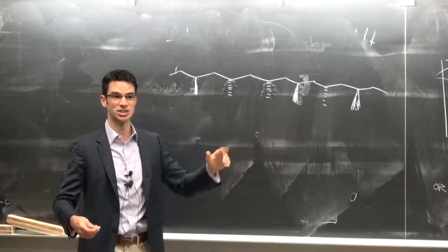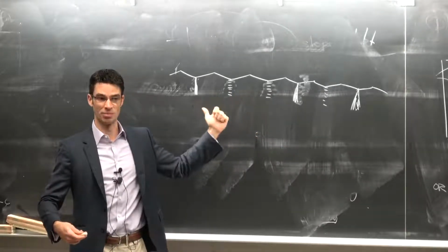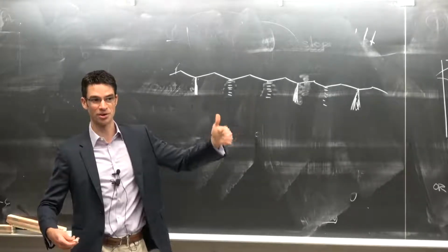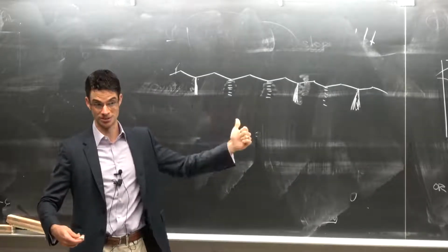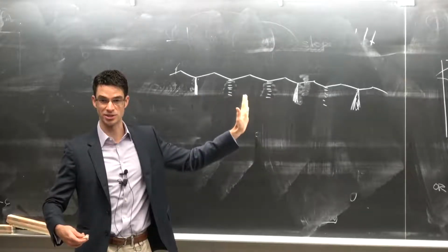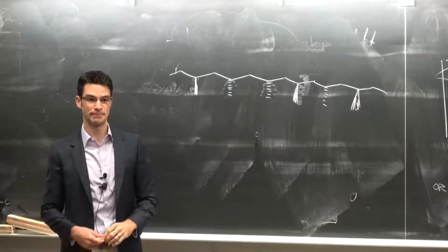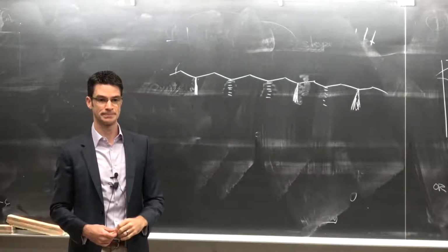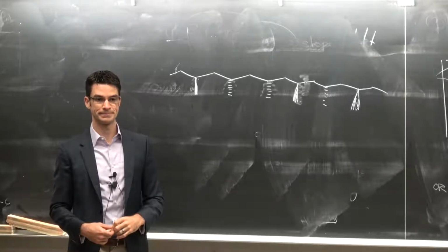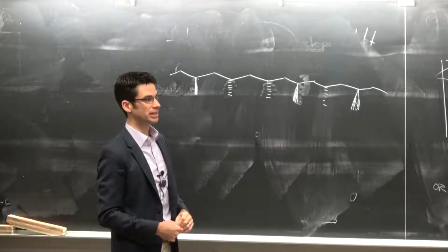But the point is, you can change the crystallinity of this material based on whether the bonds are all coming out, all going in, random, or alternating. And if there's regularity to the structure, then it can crystallize. If it's random, then it can't. Yeah. Just to slightly double, would we actually select for a more ordered structure by, say, chiral selecting from a racemic mixture of monomers? So the question is, could we